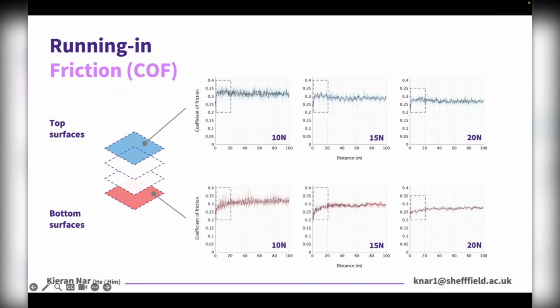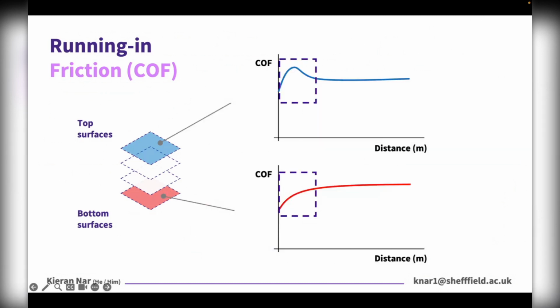Additionally, when we looked at the resultant friction data recorded during testing of both the top and bottom surfaces, we saw that over the first 20 meters of sliding, each surface exhibited different friction responses. So just to illustrate that a little bit more clearly, top surfaces exhibited this heightened transient friction response, whereas bottom surfaces exhibited these more classical plateauing increases in friction. And this suggests that these parabolic surges in friction recorded during initial top sliding, so the responses in blue, were caused by the presence of these additional asperity peaks, which provided augmented levels of resistance to sliding prior to them fracturing or yielding.